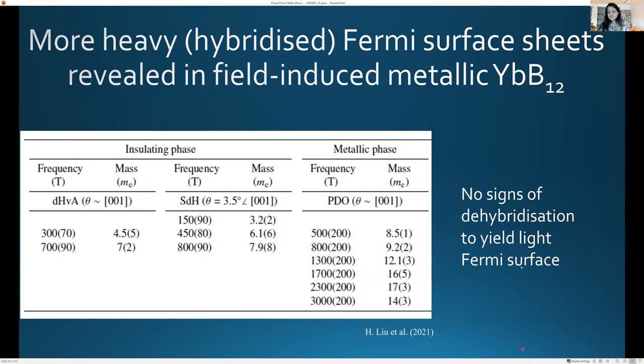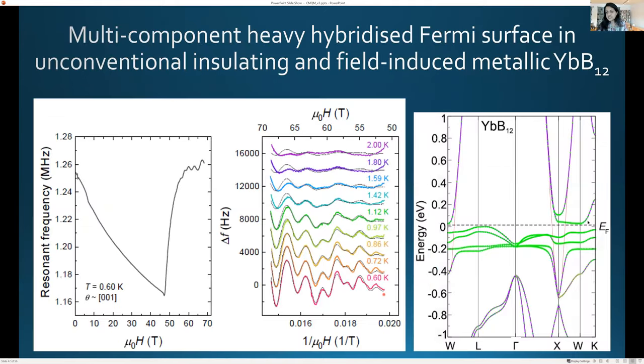So it looks like in the metallic state, the small heavy masses we see could just be from the magnetic field, which now causes the bands to cross the Fermi energy. So nothing happens to the hybridization. They're still hybridized bands, but now the Fermi energy crosses the hybridized bands and we see small heavy masses. So this would also make sense for a semi-metallic Fermi surface, because if the Fermi energy is just grazing the bands now, you would see small heavy pockets, which is what we see in the metallic state.